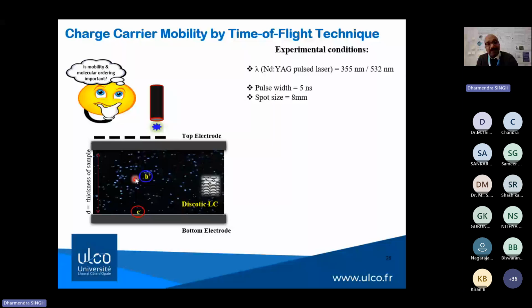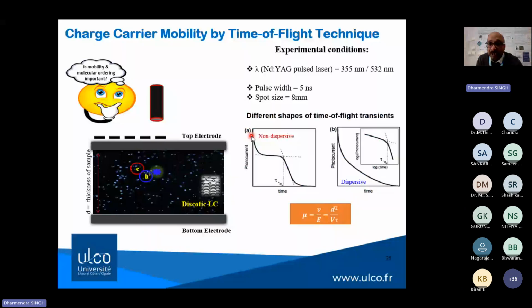When electrons or holes propagate from the top electrode to the bottom electrode, you have to record their trajectory, the photocurrent trajectory. The photocurrent trajectory can be of two types, non-dispersive or dispersive. When you have non-dispersive nature in the photocurrent curve, you can estimate the transit time by taking an intersection between two tangents. When you have the dispersive curve, you have to plot the curves on a log scale in order to estimate the transit time. And when you have the transit time, you can calculate the charge carrier mobility of electrons and holes using this formula: mu equals d squared divided by V times tau. d is the thickness of the device, V is the applied voltage and tau is the transit time.